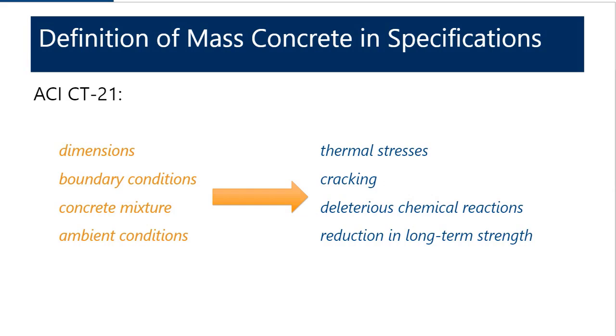ACI's definition essentially says that a combination of dimensions, boundary conditions, the concrete mixture, and ambient conditions are going to lead to thermal stresses, cracking, deleterious chemical reactions like DEF, or potential reductions in long-term strength gain, all due to the elevated heat of hydration of the cementitious materials. And that's really what makes mass concrete.